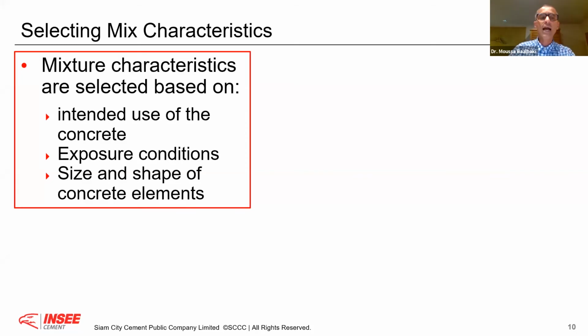And last but not least, the size and the shape of the concrete element. Because in concrete, you have constituents with different sizes. You start with the smallest, that is the cement. In webinar number 2, we'll talk about cement. The average size of a cement is, let's say, 10 micron. But the maximum size of aggregate is 20,000 micron. You see, from 10 micron to 20,000 micron. Now you have to put all this together and have a concrete that has good cohesiveness, that when you mix it and you place it, you don't have segregation and you don't have bleeding, separation. That is exactly why it is very important to master the basics. That is where we will start.